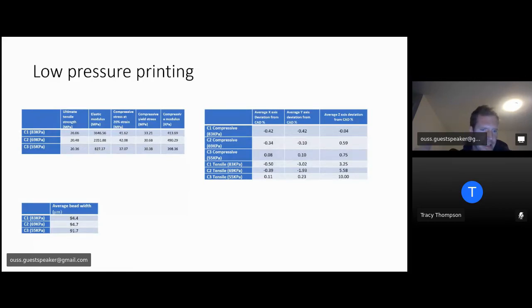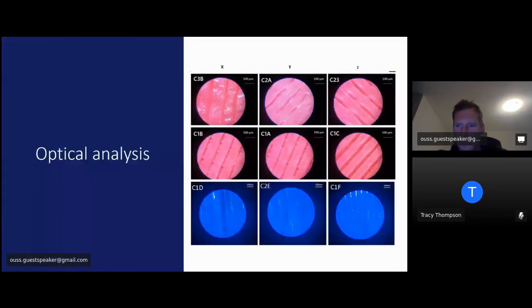So I'm seeing here my bead width is reduced, and I actually expected it to expand, because when you put things in a lower pressure, they tend to expand. But in this case, for some reason, the bead width was less. There's the optical analysis. So quite a lot of distortion there.